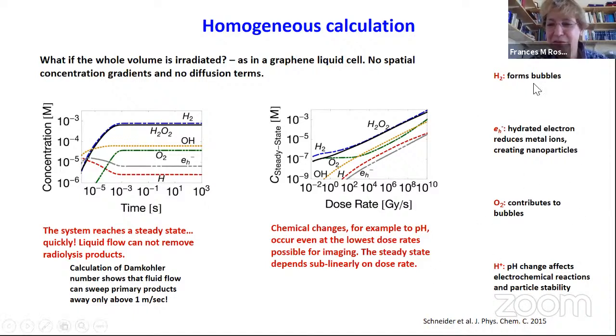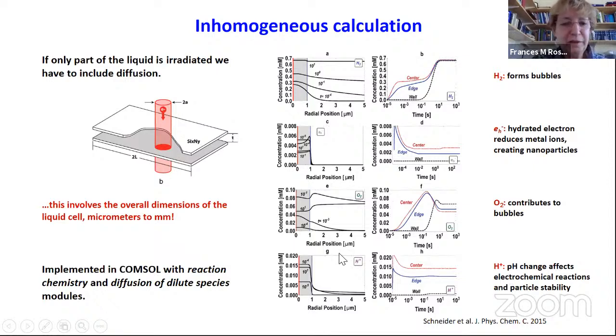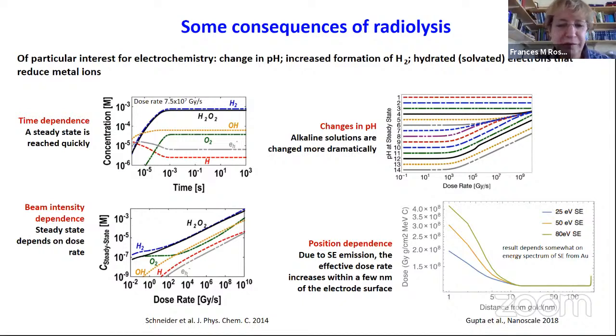And these species contribute to different things. Obviously, the hydrogen could form bubbles. The hydrated electron could reduce ions, and the H+ that's created could change the pH. If we now do a calculation where we only illuminate a little bit of the sample, like in a STEM or in a TEM with a small probe, you get similar results within the probe and some kind of transients around the edges. And so to summarize, there are lots of consequences of the electron beam striking the electrolyte. And this is one of the most interesting ones to me, the changes in pH of water as a function of the dose rate. So for example, supposing you start with a solution that's acidic, the illumination doesn't really change it.